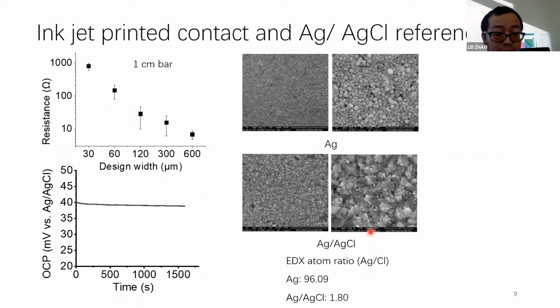Then we also characterized the inkjet-printed connections and the reference electrodes. As you can see from the resistance change here, the connection path has good conductivity, and the SEM picture shows the clear morphology change after the chlorination of silver. We also compared the reference with the standard commercial silver chloride reference electrode. As shown in this curve, within half an hour, there's nearly no potential change compared to the standard reference electrode.